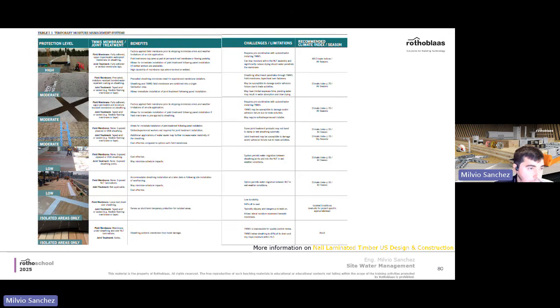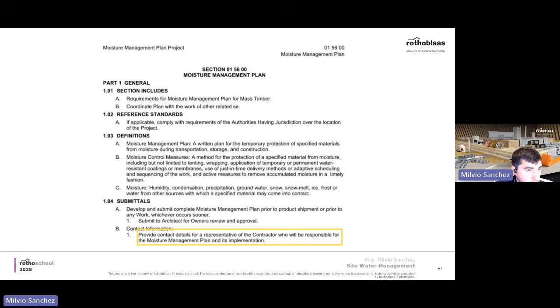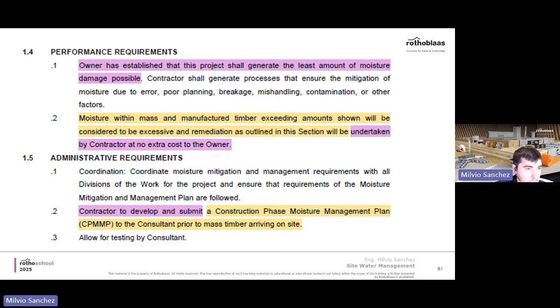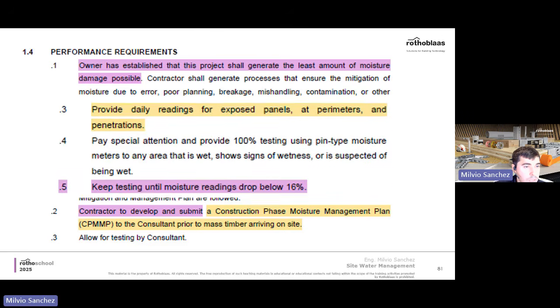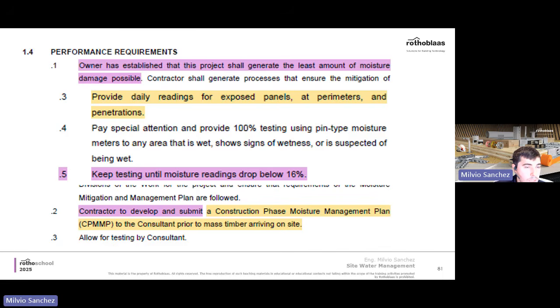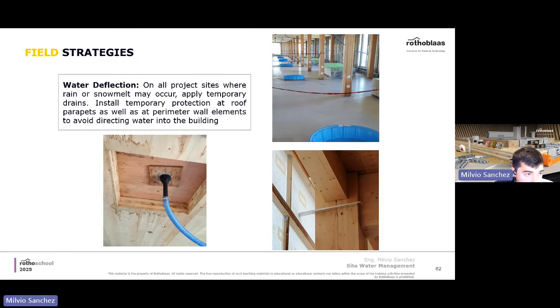Also the Nail Laminated Timber US Design Guide. They also talk about recommendations for protection only in isolated areas, going up to the high protection level where all of the panels are wrapped up. But anyways, the contractor is the one responsible in the specifications to make sure that there is a moisture plan in action and it's being implemented. And also, usually it's written that moisture exceeding this amount, let's say, should be considered excessive and remediation should be taken by the contractor. And also moisture monitoring has to be done extensively to keep the moisture readings below 16%, especially before enclosing the projects. And some field strategies that may happen are water deflection as much as possible, or temporary drains.